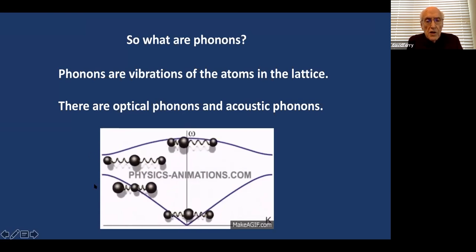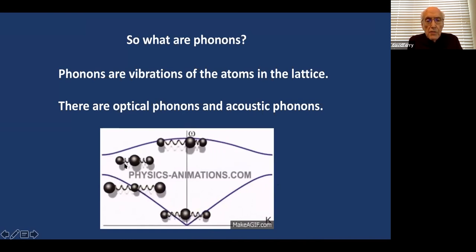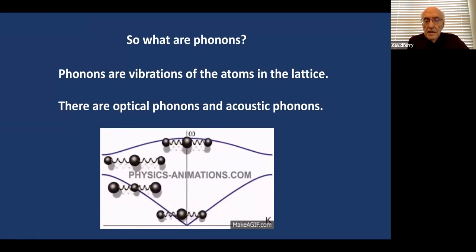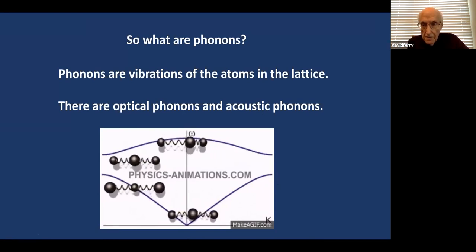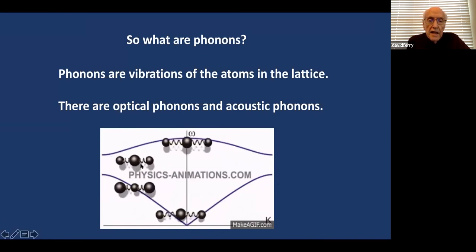Now, over here at the zone edge, it's a little more complicated. This is an optical branch and this is an acoustic branch, but in the zinc blende materials, you have a heavy atom and a light atom. Gallium and arsenic. Arsenic is heavier. And on this branch, the heavy atom is sitting still and the light atom is vibrating around it. Okay, and here, the light atom is sitting still and the heavy atoms are vibrating around it. So they're slightly different. And so that affects how the electrons themselves in the band structure get from one side to the other, but it's an interesting aspect of how things are going.